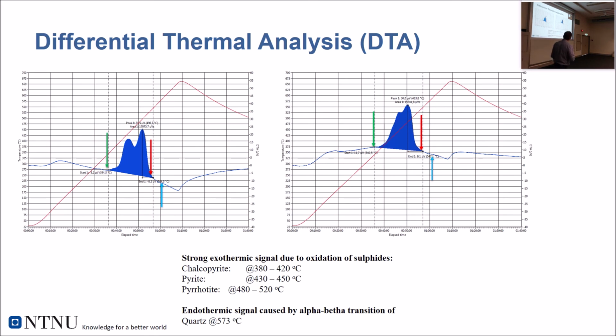So we see that at 573 degrees we have the endothermic response from the phase transition of quartz in both samples. We also see that from 340 degrees up to 540, we have a huge reaction for sulfides. However, we cannot from these reactions say if it's pyrrhotite, pyrite, or chalcopyrite. So we can only say that there are sulfides in the sample. And that's how they say it. Because you have two peaks, they interpret that you have pyrrhotite together with pyrite. If you had only pyrite, they say you would only have one peak. You can't say exactly how much by weight you have, even if you have two peaks. That's the indication of pyrrhotite we use today to say if an aggregate is accepted or not.